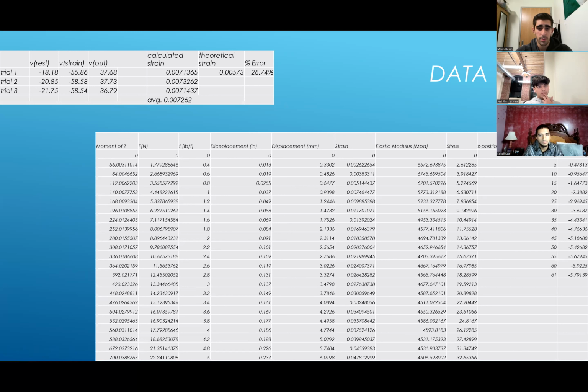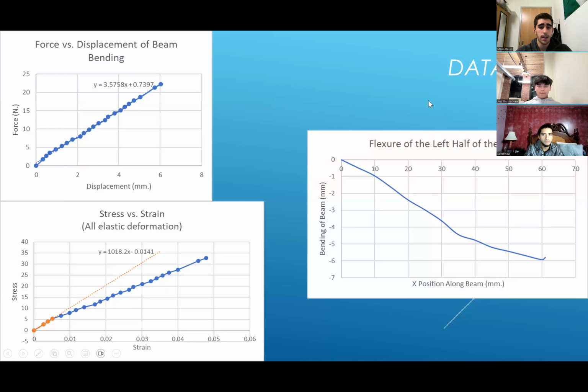And then in the second part of the data, using the measurements of the sample itself and the force versus displacement data, which was initially in pounds force and inches, which we then converted to newtons and millimeters so it would be easier to work with, we were able to calculate the moment about the z-axis, the stress and the strain, the elastic modulus at different force and displacement values, along with the vertical displacement along different points of the X position along the beam when under 3-point bending testing.